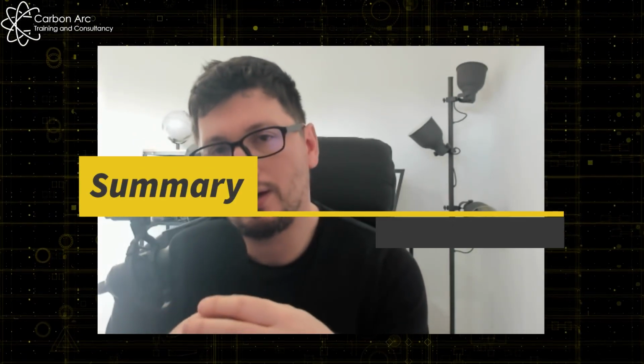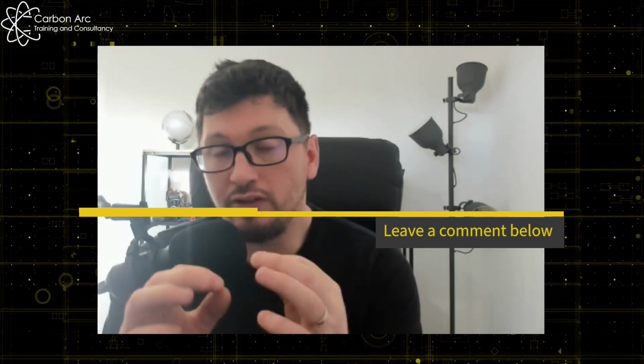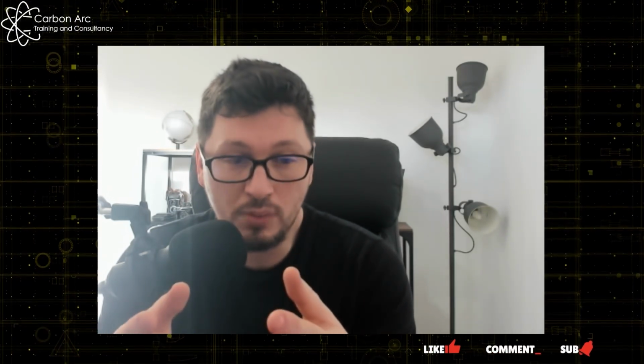So as a recap, we have a welding process which is very versatile. It is fairly cheap and easy to transport because it's fairly small and portable. We have a range of welding consumables that we can use of various different strengths and uses, but they fall into 3 categories. So basic is a high calcium carbonate. They provide low hydrogen welds and are suitable for high quality welds with good mechanical properties. Our rutiles contain titanium dioxide, offering a smooth arc and easy slag removal, and they're ideal for general purpose welding.